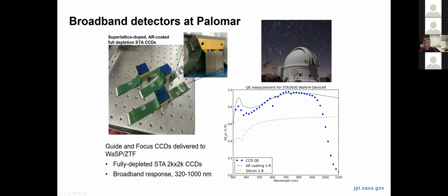Here's an AR coating, again, that was optimized for this WASP ZTF application, which is a ground-based instrument. So an AR coating that maximized response at visible and near-infrared wavelengths. This is a hafnium oxide, silicon oxide-based coating, showing again some of the interesting packaging that was used on these devices to allow them to be butted close together.